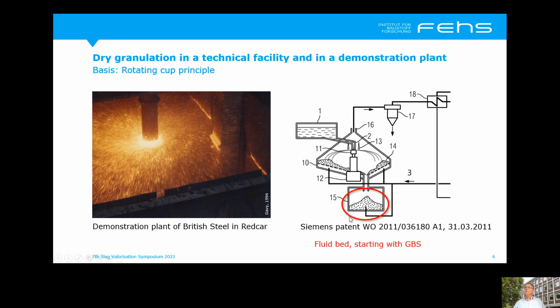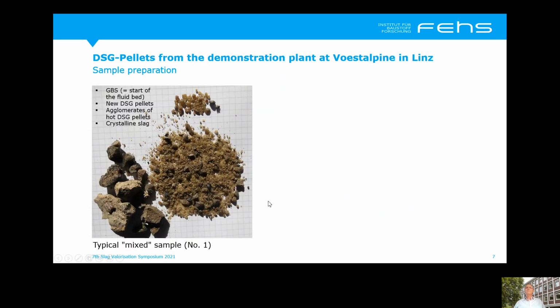But in the beginning of the process of the test, you have to start with wet granulated blast furnace slag to be able to have some material inside the installation. After the test, we got mixed samples consisting of classical wet granulated GBS, newly produced dry DSG pellets, some agglomerates of the pellets, and some crystalline slag.